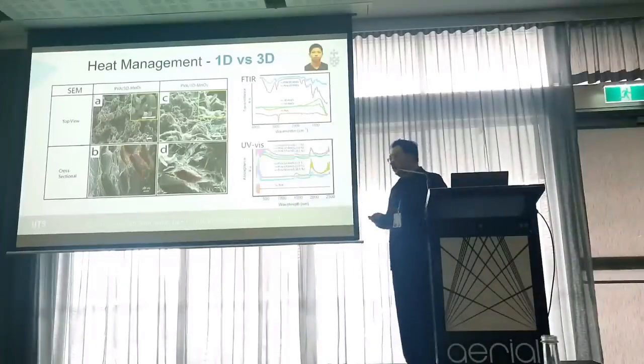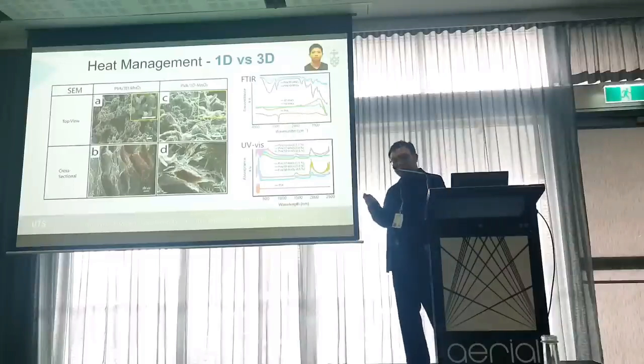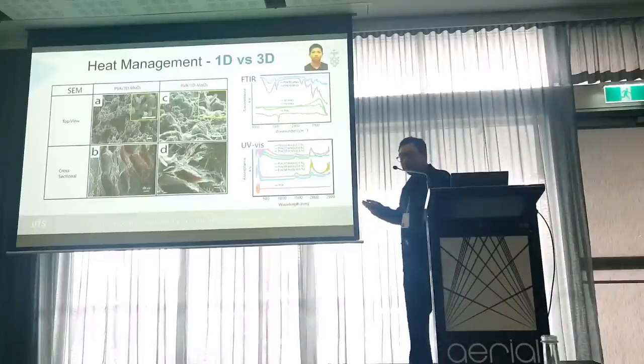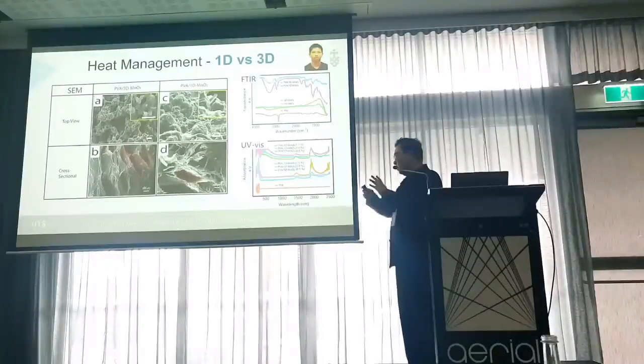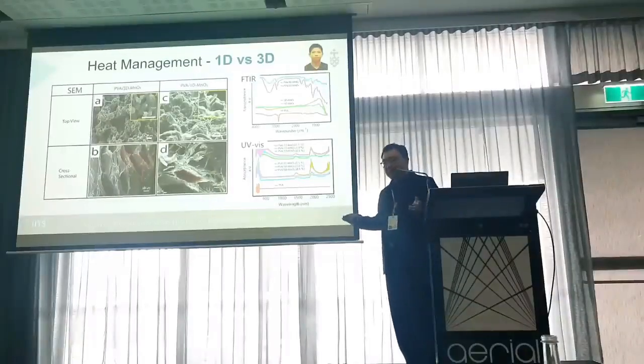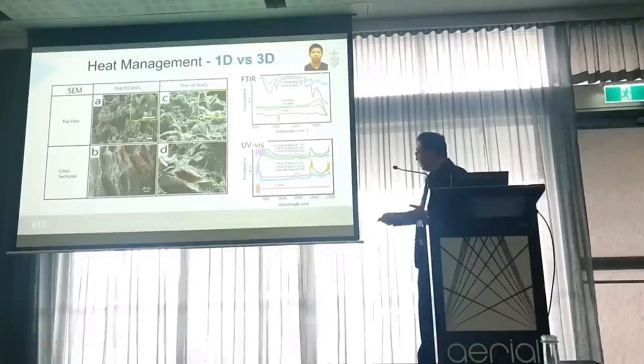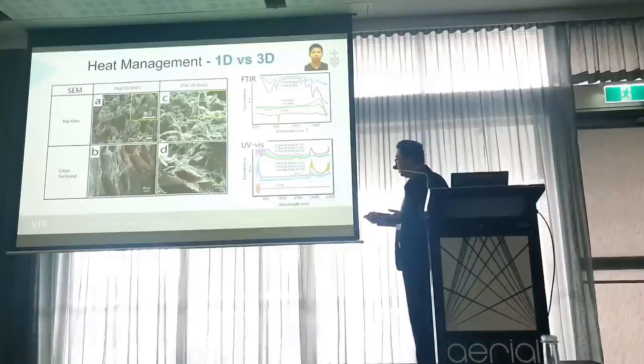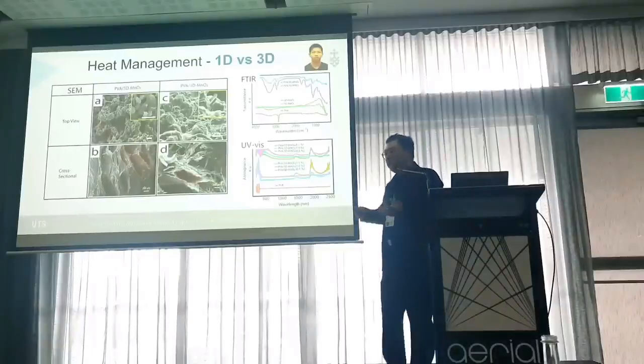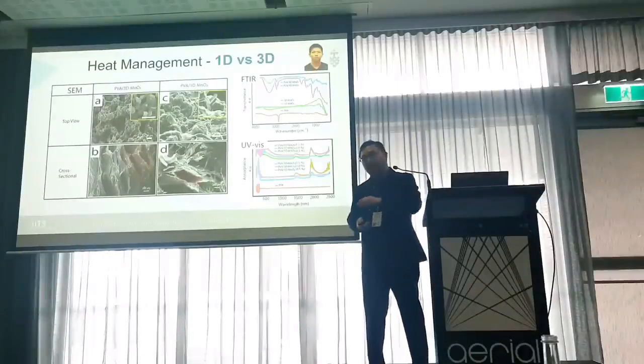And you can see when we introduce black colored photothermal materials into the hydrogels, they can efficiently absorb the solar irradiation. They usually show a very broad solar absorption spectrum from 300 nanometers to 2500 nanometers. In contrast, the pristine PVA samples, as you can see, almost have no solar absorption above 400 nanometers.